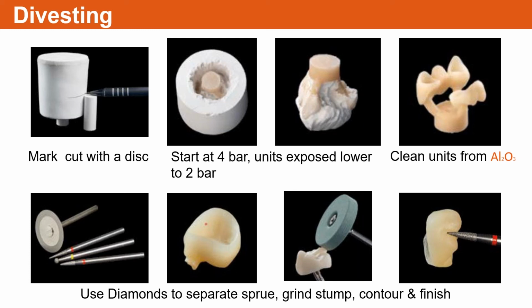So we just have to sit there and make sure that we don't overly pressurize our aluminous oxide. Otherwise, this stuff is glass. It's a lithium disilicate, a glass material, glass matrix. When you have too much pressure with aluminous oxide, it's hitting against that material, and as it hits, it builds up energy. If you were to turn off the lights and look at where you're sandblasting, this is true with Zirconia frameworks as well. You've got to make sure that you adhere to the low pressure so that you do not create sparking on this material or overheating, because it'll disrupt, it'll change, and maybe fracture your material.